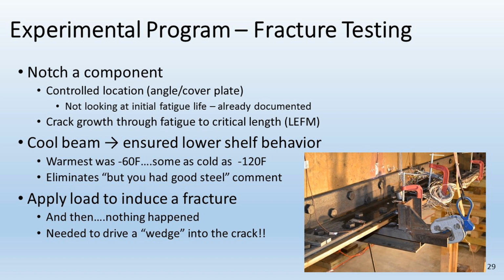As I said earlier in the presentation, prior to the fracture control plan, we had no toughness requirements. So we have some steels and some bridges that, I don't want to say they're bad or brittle, they just don't meet the modern specifications. They might be quite low in terms of their CVN energy, single digits, for example, at minus 30 Fahrenheit. We wanted all of our tests to reveal the absolute worst case, brittle steel, cold temperatures, so that we could apply it to the entire inventory without having to have caveats, like you need this toughness so you'd have to go measure it, or it only works in South Texas. This way, we have the worst case, and we know that it works for all of the steels.